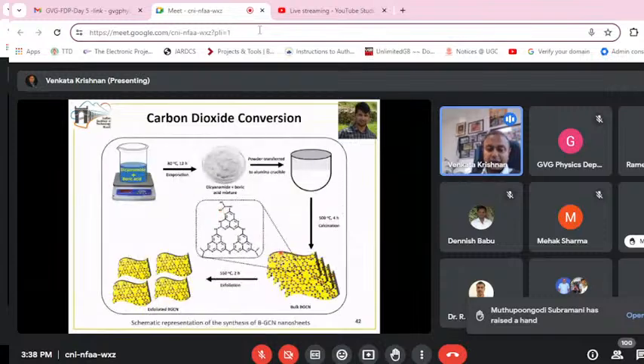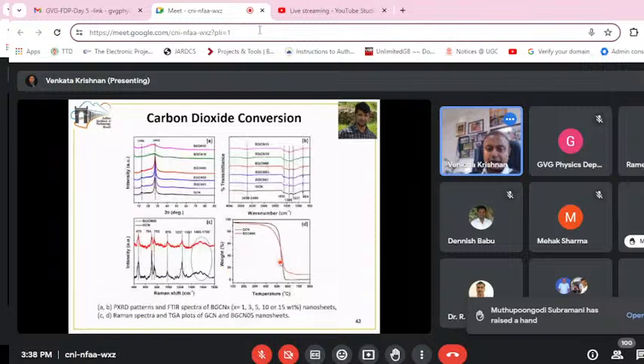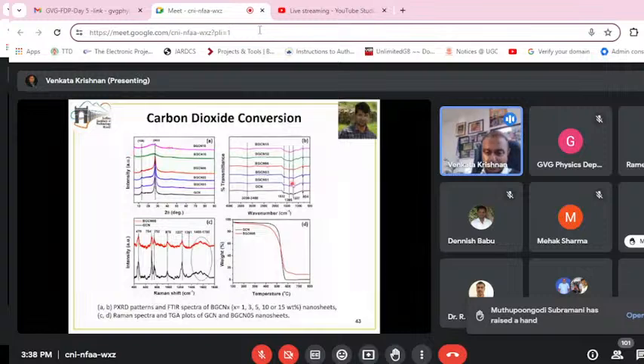This is how we prepared the catalyst. Similar to the previous cases, we did a detailed optimization of the catalyst preparation, wherein we took boron in various different proportions from 1 weight percent to about 15 weight percent, and then did a detailed characterization using X-ray diffraction, FTIR spectroscopy, Raman spectroscopy, and thermogravimetric analysis in order to understand the successful preparation of the catalyst.